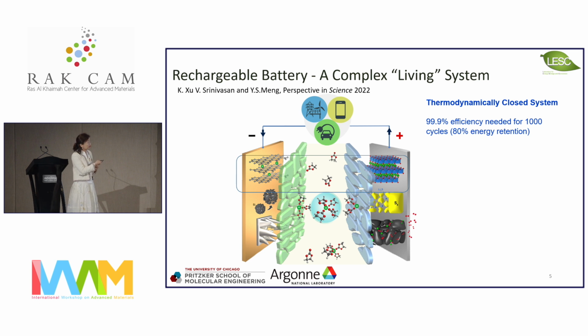And during this process, because battery is a closed system, just look at your cell phone. No matter can go inside and come out during the operation. So you probably don't realize that every time you're charging your battery, you are making a mini chemical plant. You are actually transferring all the electrical energy into the chemical energy because the lithium in the lithium cobalt oxide is very stable. When you use the electricity to drive it to the graphite, lithiated graphite is extremely reactive. So you make these two very unstable materials, and that's where it can actually automatically release chemical energy. Where the lithium travel back to lithium cobalt oxide, that's where you got the electrons. So this closed system has to have 99.9% efficiency in order for your device to work for 1,000 cycles.